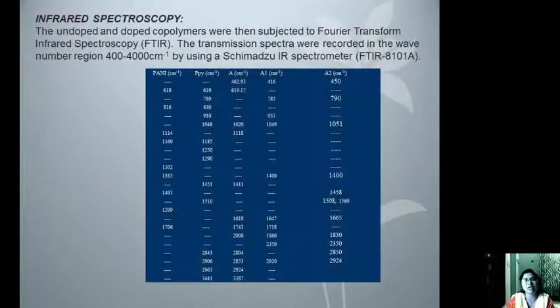NiCl2 doped sample. Further, infrared spectroscopy was utilized to understand the typical linkages of the two monomeric units along with the initiators. Herein I have prepared a table in which the peak positions of pyrrole, aniline, as well as the self-doped, that is the as-prepared copolymer, along with the undoped and the doped copolymer are shown.